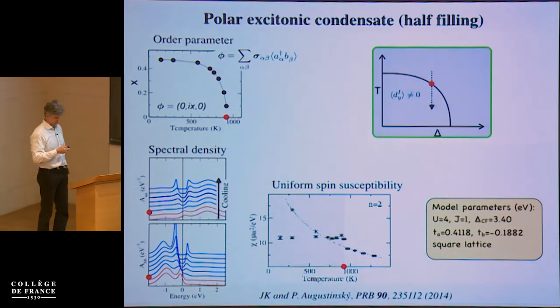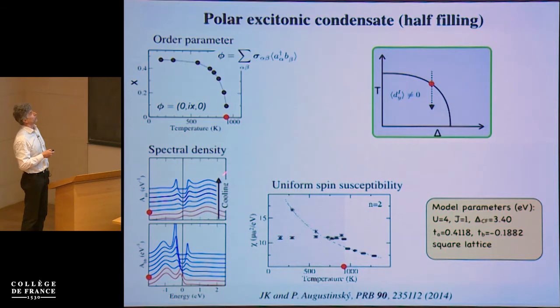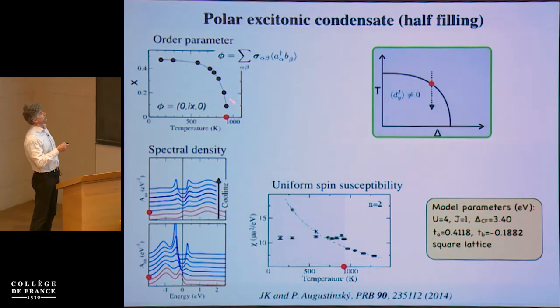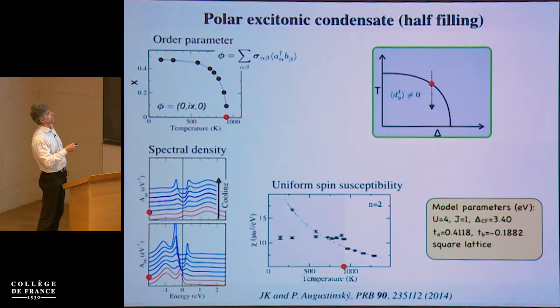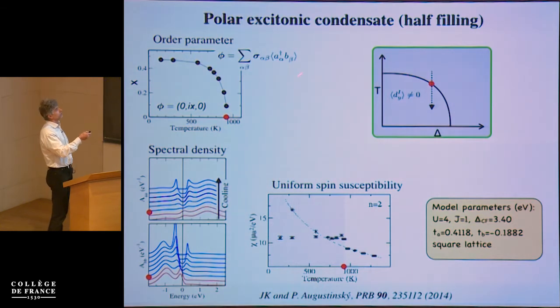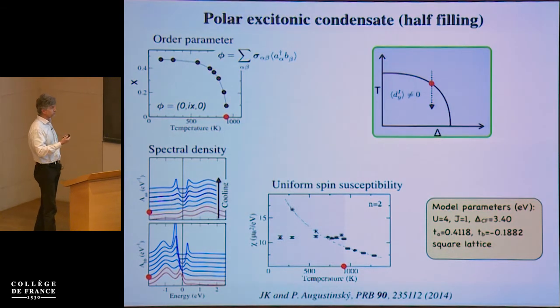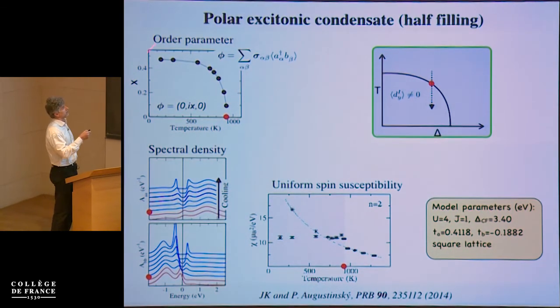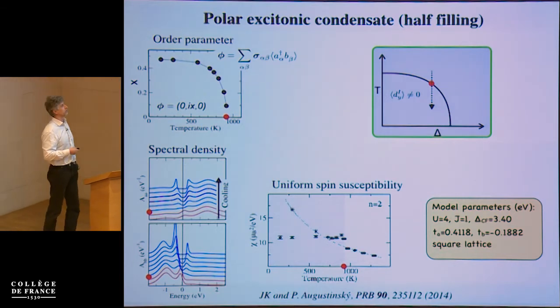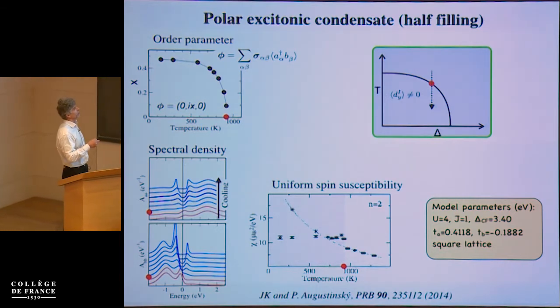I'm going to talk about this a bit more later. So this is the first numerical result. This is temperature, and here we measure the order parameter, and you see a typical mean field-like dependence of the order parameter. So indeed, we get a finite expectation value of this orbital off-diagonal spin triplet order parameter, and we find that the condensate is actually of the polar type. In a moment, I'm going to explain how we can see it.